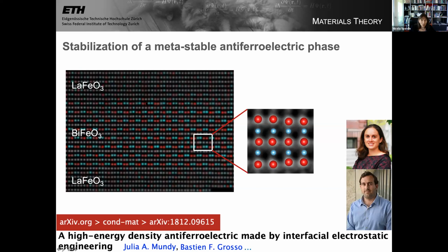And we want to look at the layers in the bismuth ferrite. Remember when we looked at bismuth ferrite previously, we're seeing the bismuths again. When we looked at bismuth ferrite previously, the bismuths formed a nice kind of square array because they all shifted in the same direction to make the ferroelectric polarization. In this case, you see that Giulia's blown up a kind of section here. We have this pattern of two bismuths going up, then two bismuths going down.